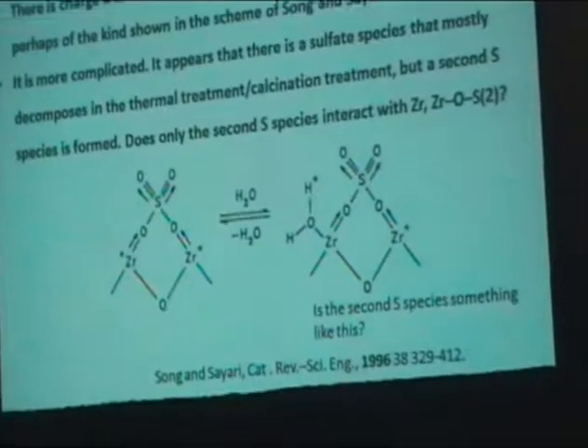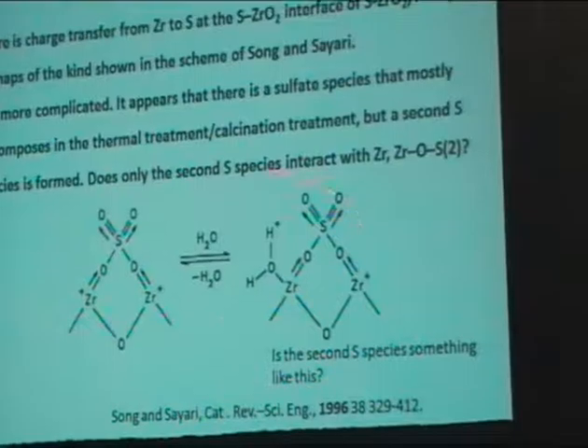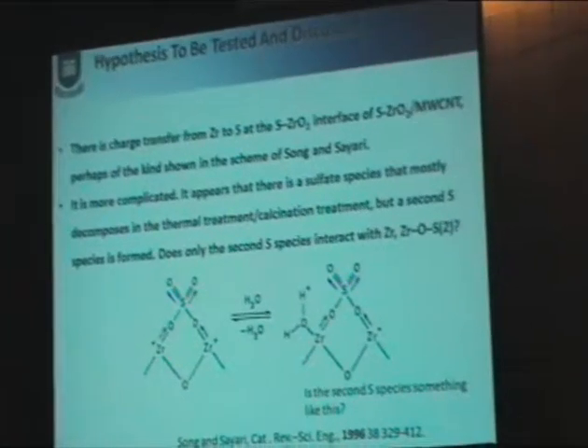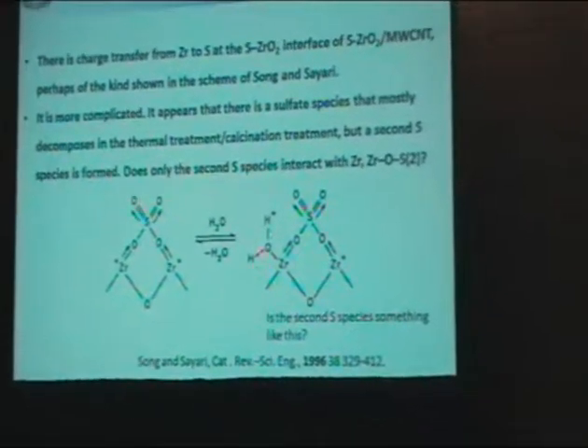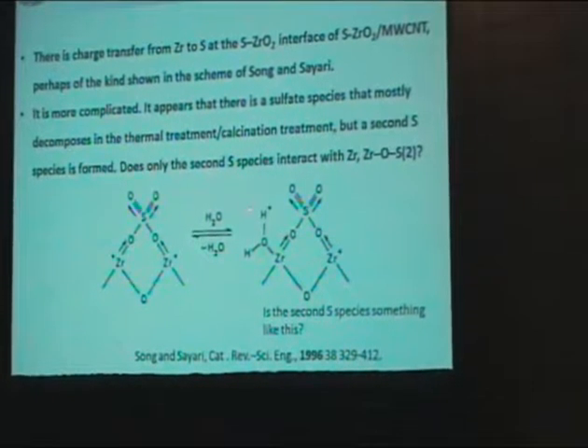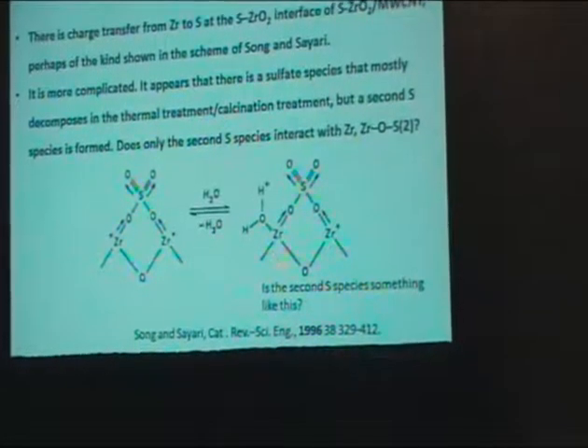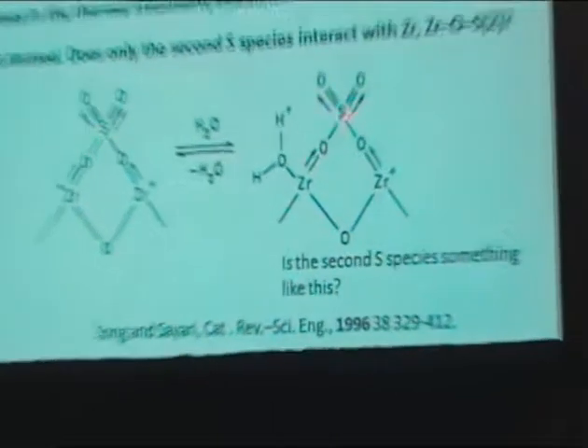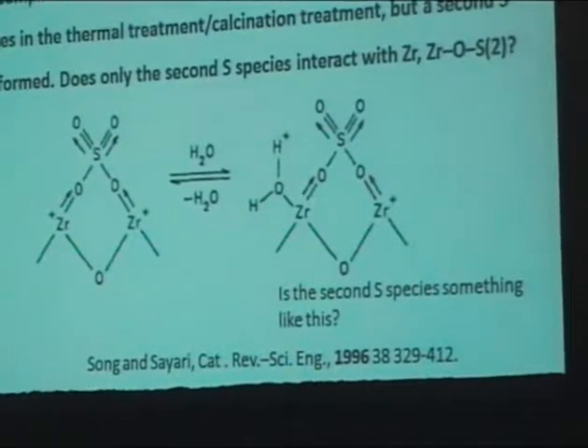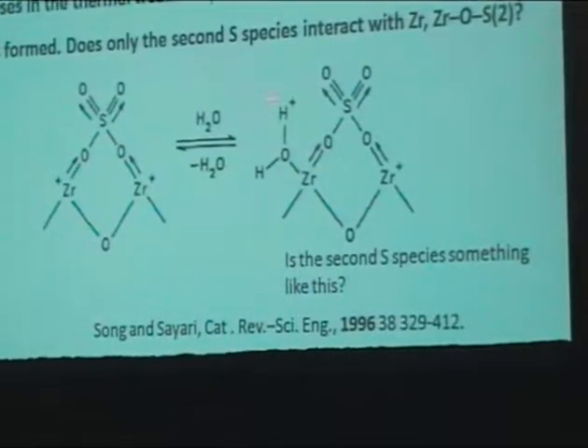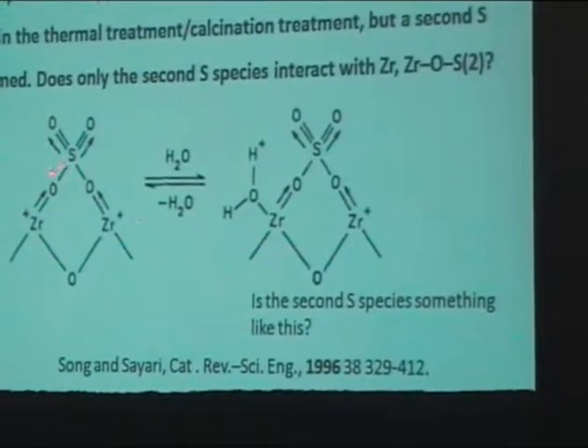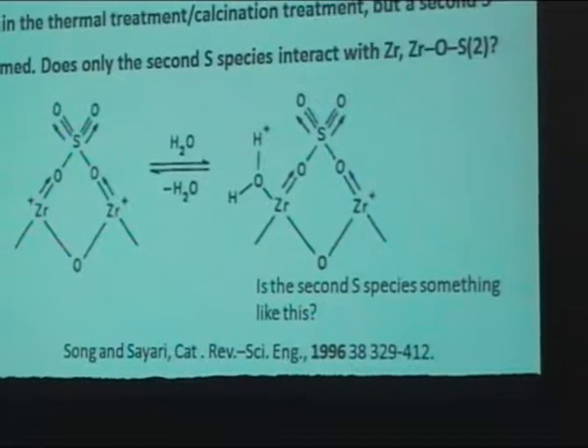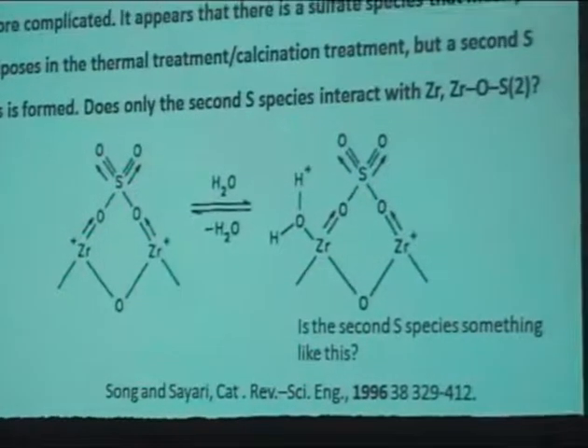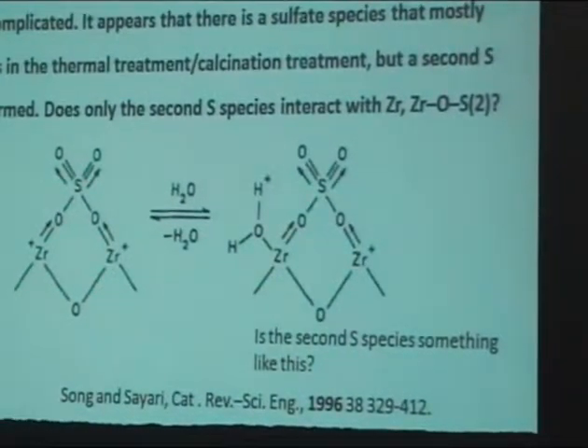Now, there are several reviews in the literature of sulfated zirconia, and there are, I don't know the exact number, but perhaps as many as 30 pictures of what the sulfated zirconia sites might look like. Here's one of them. And one of the things that I want to talk about is the charge transfer that we can see as we look at the zirconium edge or the oxygen edge and the sulfur edge. And with respect to the sulfur edge, I'll try to convince you that there really are two species, a sulfate species, and then whatever the second species is that is actually the catalyst. And so what is that, and how does it share electrons? I guess that is a subtitle for me.